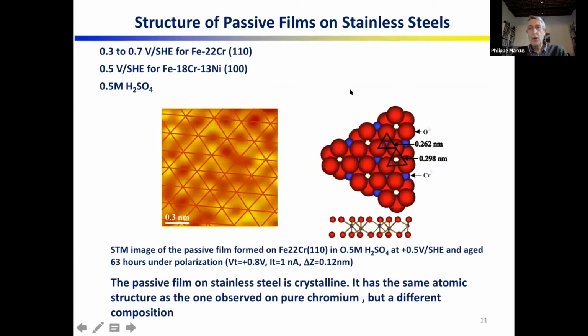So this kind of work was extended to several alloys, and I'm going to show just the example of stainless steel, on which both on austenitic stainless steel, iron, chromium, nickel, or ferritic stainless steels, we also observed a highly crystalline layer. You can see here the very high resolution image. This is 0.3 nanometers. And again, each of these bright spots correspond to position of atoms. And this corresponds to the structure of chromium oxide, alpha Cr2O3. So the passive layer on stainless steel is crystalline.